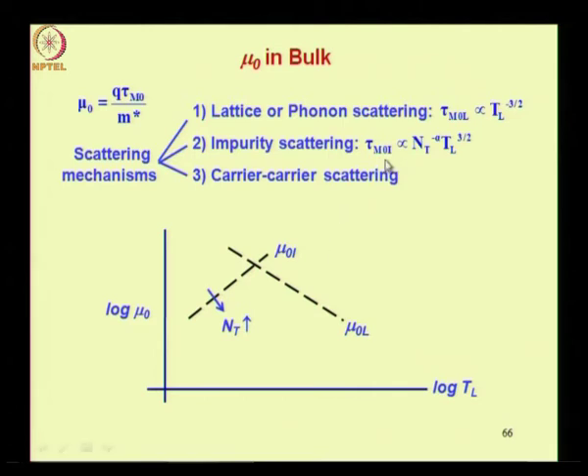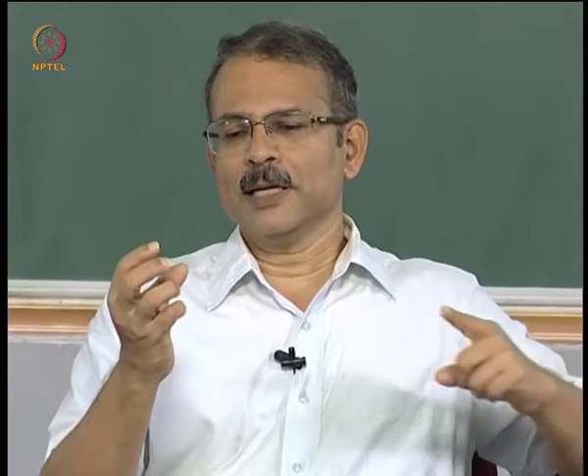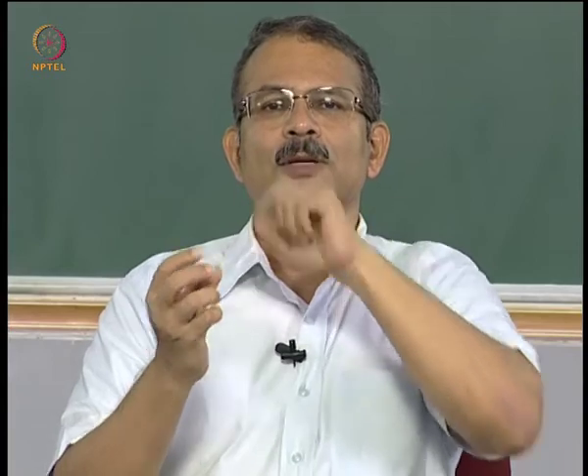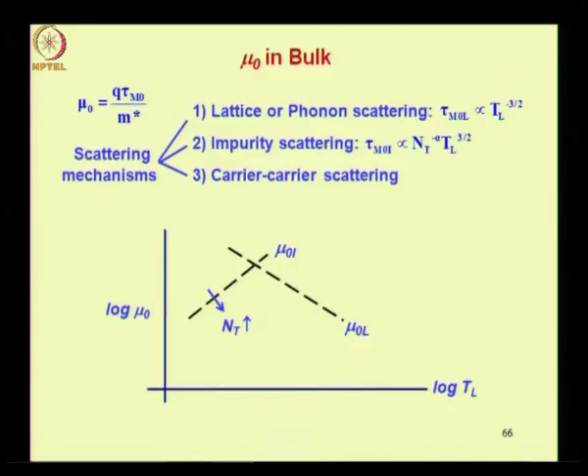Repeating the similar procedure for impurity scattering, you have the momentum relaxation time due to impurity scattering proportional to Nt power minus alpha multiplied by TL power 3 by 2. Recall that we had said in our earlier module that impurity scattering will increase with total impurity concentration, therefore the impurity concentration appears in the denominator, that is why the negative power alpha. Further, we had also remarked that if the carrier moves very fast past the impurity atom, then the amount of scattering will be reduced. So you have an impurity atom and the carrier is moving very fast, then the amount by which the carrier will get scattered would be less, and therefore since the thermal velocity increases with lattice temperature, the amount of scattering decreases as lattice temperature increases for ionized impurity scattering. That is why this kind of a behavior.